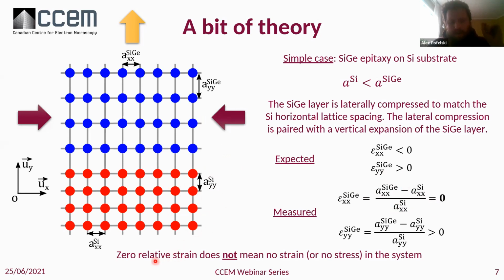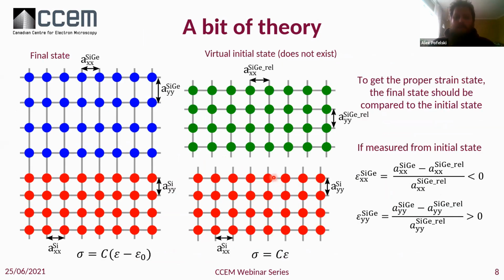So this is very important to remember, that the zero relative strain does not mean non-strain or no stress in the system. So this problem is coming from this reference, and it could be possible to overcome this issue by comparing it to a proper initial state. So in this case of this type of growth, what we would like to compare the silicon germanium to is the silicon germanium layer, not grown on the silicon's lattice, but just at its relaxed state. So if now we do this comparison here between this red and the green lattice, we will find the proper deformation state. The problem is that this initial state actually doesn't exist.